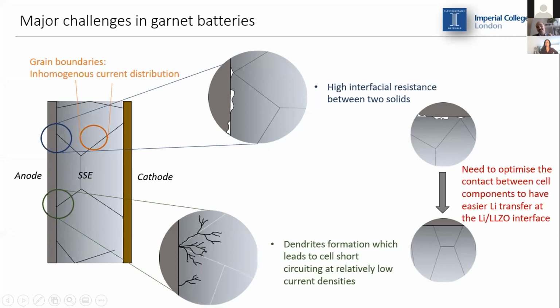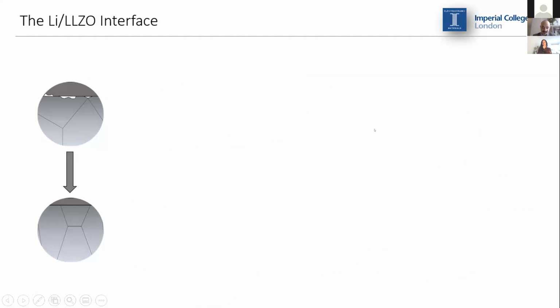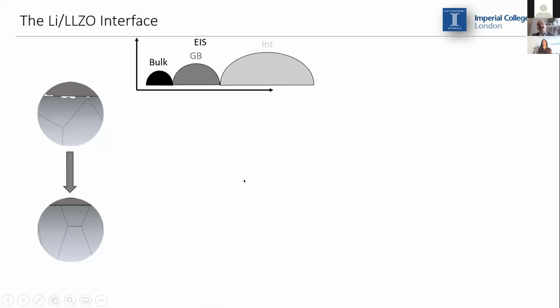So there is a need to optimize the interface between metallic lithium and the solid electrolyte in order to have an easier transfer of lithium ions from the metal to the electrolyte when we discharge the battery, and the other way around when we charge the battery. Other groups in the literature have reported several ways of improving the contact in between the lithium and the solid electrolytes. I must mention that we use a technique called electrochemical impedance spectroscopy in order to have an idea of how easily the lithium ions can move in our electrolytes.